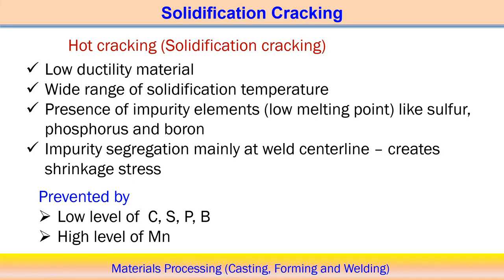High level of Mn basically helps to avoid formation of solidification cracking, because Mn can react with carbon, sulfur, phosphorus, and boron to reduce their effect. From that way, the solidification cracking phenomenon can be reduced in the presence of a high level of Mn in the solidification process.